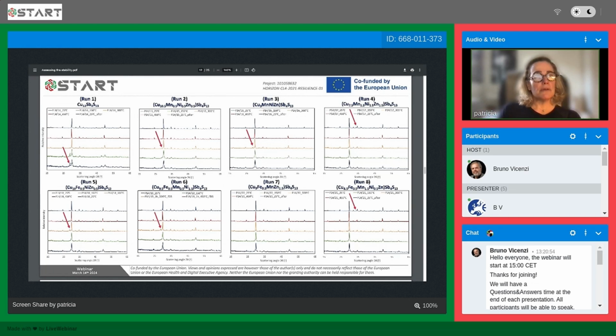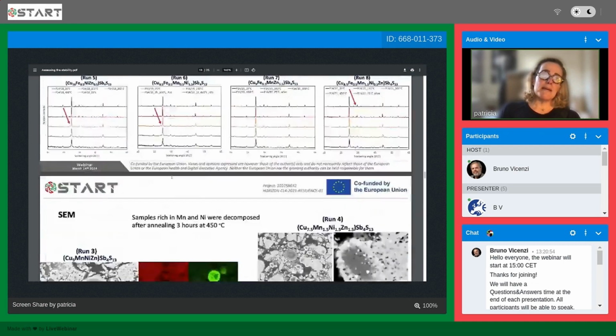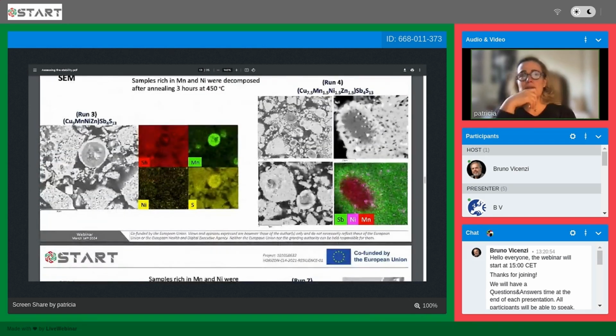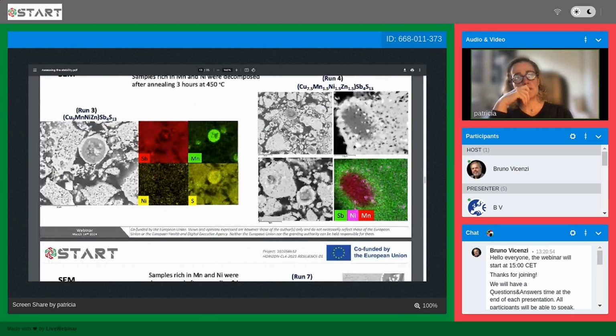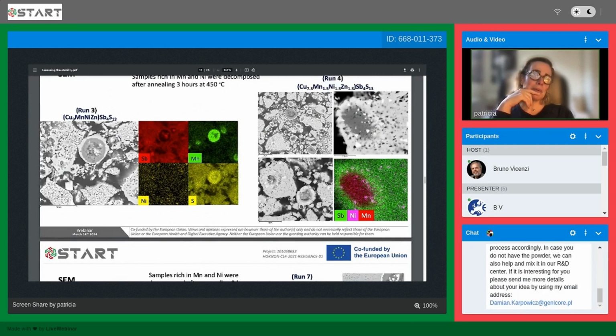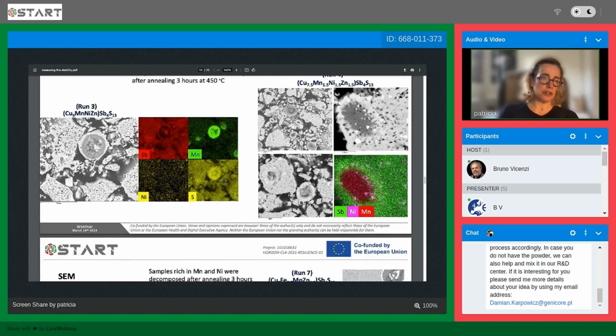And when you look at this, you see some peaks, but most samples are essentially tetrahedrite. But when we look at the SEM images, what we see is that we have a lot of things going on. There's a lot of decomposition. And the most important aspect that we take from this initial study was that XRD is probably not the best technique, even if you perform annealing while you're acquiring your XRD patterns, because most samples had very complex microstructures.